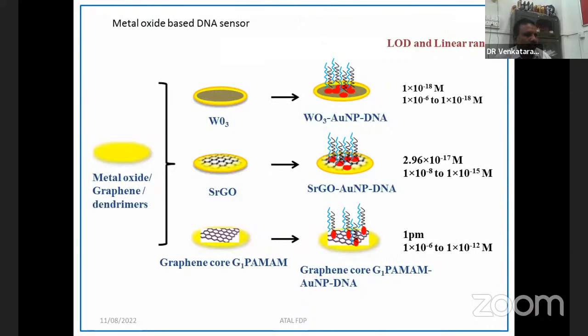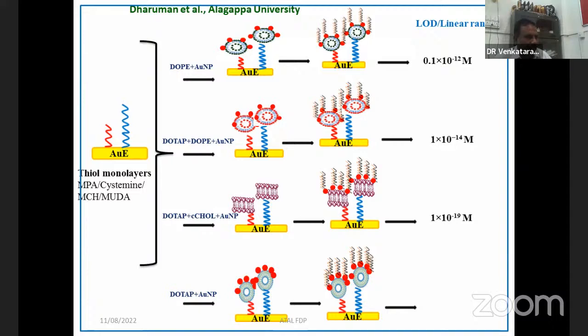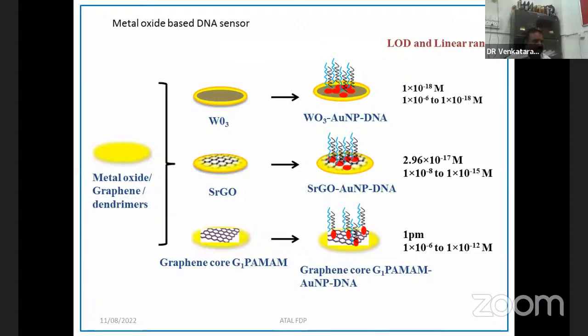And recently we also replaced the lipid layer, because with lipid layer we get quite reproducible results only sometimes. In order to avoid that, we tried to change the matrix for attaching the strand, using metal oxide. Here we took the tungsten oxide gold nanoparticle, and then we put it to the single strand and double strand. Again we also use a graphene core. All these things are compared here. When you change the surface chemistry, the concentration of DNA sensing limit and the linear range are also changed. This is what I would like to convey here.